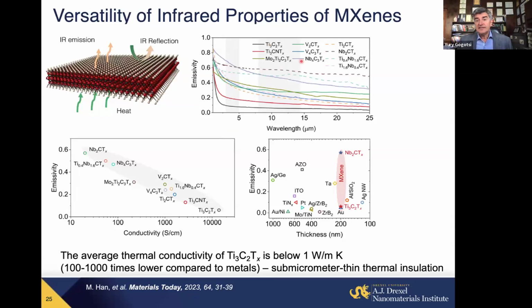For example, depending on composition of MXene, MXenes can either emit heat, infrared radiation, very, very well, for example niobium carbide MXene. Or they can emit very little, keeping all the heat shielded. So they can cover the range from polished metal to insulators, really, emitter materials. So if you want to have a space heater by electrical Joule heating, you use niobium carbide. If you want to put a coating preventing infrared heat radiation coming through a window, you can use titanium 3C2 MXene. But there is an important difference.